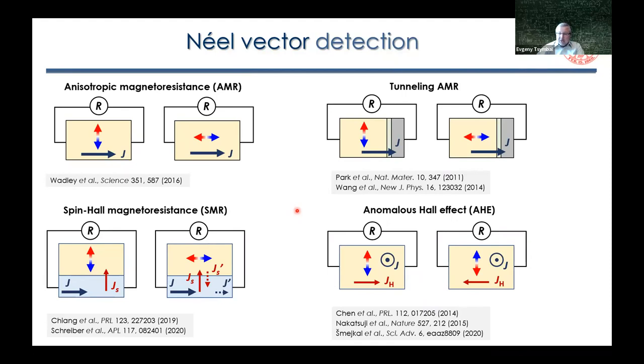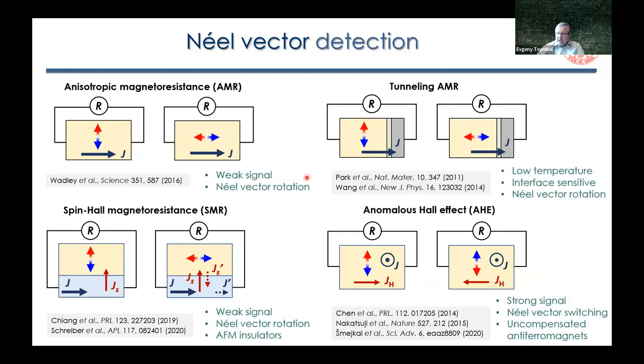So the advantage of anomalous Hall effect, I would say, as compared to all other effects, is that it changes sign depending on the Néel vector orientation. But it's limited to certain types of antiferromagnets where by symmetry, we must have an uncompensated magnetic moment. So all these effects have their advantages and disadvantages. So I list some of them here. One of the major disadvantages of AMR and SMR is a relatively weak signal. Also, these effects are sensitive to Néel vector rotation, but not sensitive to the switching of the antiferromagnetic order parameter,